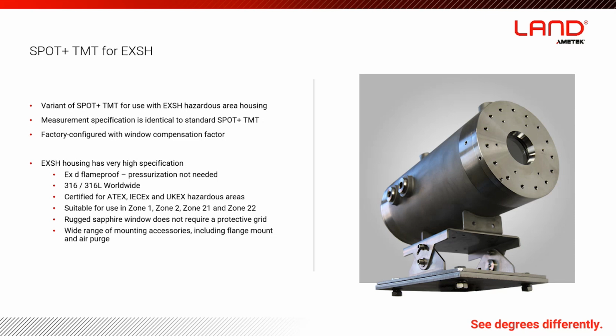And the EXSH housing is extremely high specification. As I said, it's flame proof, so there's no need for purging or pressurization. It's made from 316 or 316L stainless with a sapphire window, so it's extremely tough. Certified for ATEX, IEC-EX and UK-EX hazardous areas, so it has worldwide certifications. So you can put it pretty much anywhere you need to in a hazardous area.